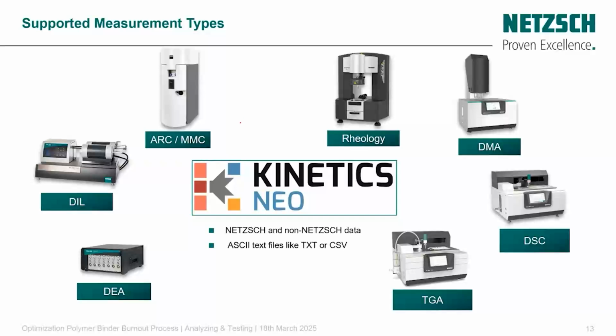So Kinetics Neo supports all types of measurement: rheological measurement, DMA, dynamic mechanical analysis, differential scanning calorimetry, DSC, thermogravimetric analysis, dielectric analysis, and dilatometer. For example, in this case, we have experience with the dilatometer when doing process optimization during the sintering of ceramics, and also we can use the ARC, accelerating rate calorimetry. For Kinetics Neo, we can use non-NETZSCH data, and usually it's an ASCII file like a text file or CSV.